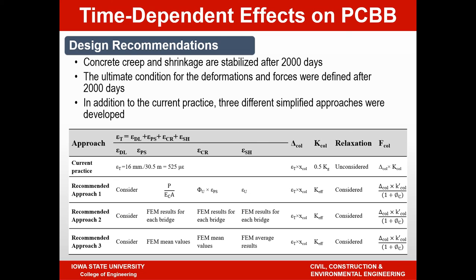We have 525 microstrain assumed as the superstructure shortening, but that does not include the pre-existing strain. And as I said, this is the issue that we are discussing with Caltrans in terms of how that should be captured. But let's focus on the three different approaches that we have included. You could see if you look at how the pre-stress is captured, in the first approach, we just simply take the axial amount of pre-stress that's been applied, divided by the modulus, divided by the cross-section of the superstructure, which will give you some average pre-stress strains.